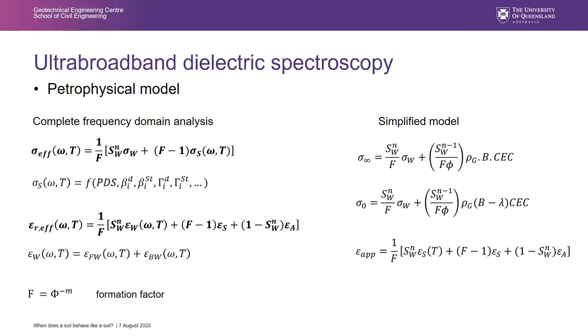The problem is that the conductivity of the solid part is very, very complex to compute and depends on the particle size distribution, the ionic diffusion in the diffuse and in the Stern layer, and other parameters. At the moment there are models that exist that are not complete, but there is a lot of work being done to compute these electromagnetic properties. Then you have a similar equation for the high frequency permittivity, which gives us the possibility to express the permittivity. This is still work in progress. And in parallel, you have what we call the simplified model, which gives us the ability to compute low and high conductivity and apparent permittivity more easily with simplified equations.